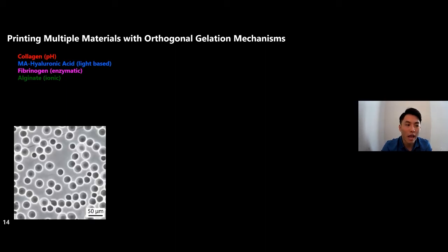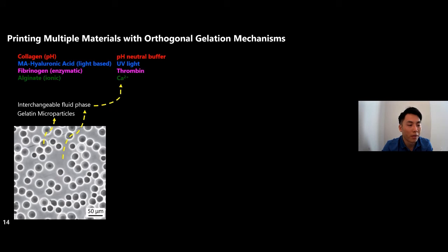And so this all happens inside a support bath. And this is where it gets very interesting. Within the support bath, we have these gelatin microparticles, and surrounding these gelatin microparticles, there's this interchangeable fluid phase that is critical for allowing us to print with multiple materials all at the same time. Because in this fluid phase, we can actually start to think about incorporating a pH neutral buffer.